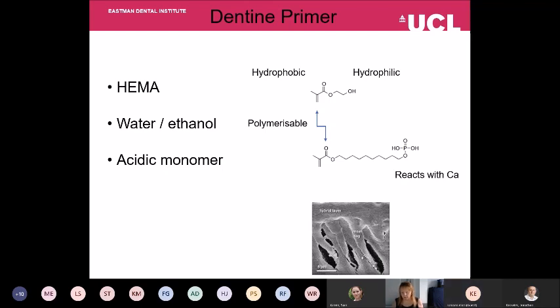Additionally, you often find acidic monomers in the primers. What these have is the methacrylate group, as in HEMA, but often a phosphate group or a carboxylic acid group that combined with calcium in the apatite, providing a bond between the resin phase and the remaining apatite.